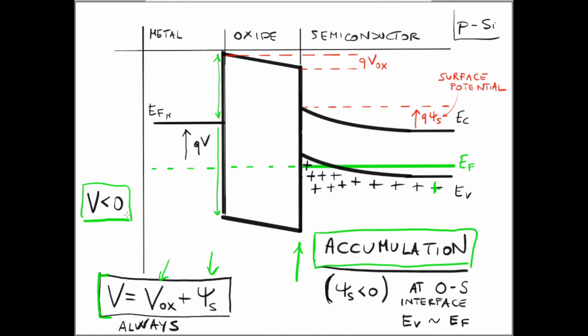So in the case of P silicon, when V applied to the metal is negative, we are in a situation that we call accumulation. This is also indicated by the fact that, as you see, ψs here is negative. Remember that q is the charge of the electron, so it is negative. For the band bending to go upward like that, ψs is negative. So accumulation is characterized by the fact that ψs is negative. And as we've said a moment ago, it means that at the interface between the oxide and the semiconductor, the valence band is very close to the Fermi level. Remember, this is for the case of a P silicon.